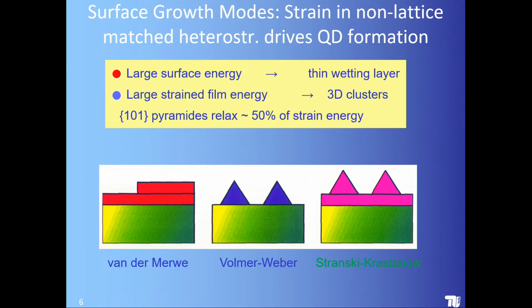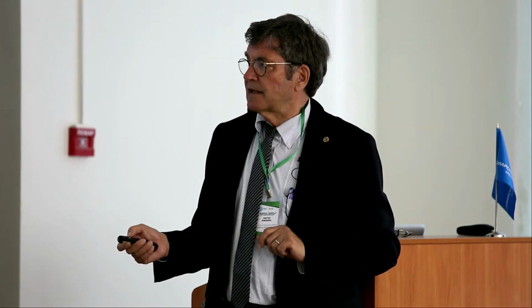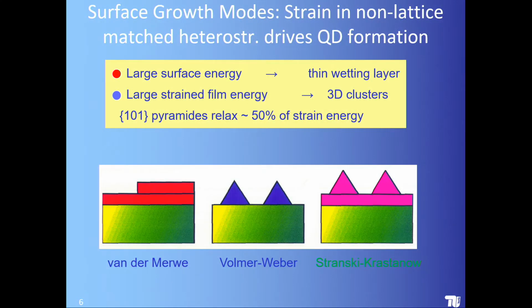So we have two classical growth modes. The Frank-van der Merwe growth mode, which is based on large surface energy. Then you get a thin wetting layer if you deposit a second material on top of a first material. Then you get layer by layer growth. That is the Frank-van der Merwe growth. The second growth mode, if you have large strain film energy, results in three-dimensional clusters. That was discovered by Professor Volmer, professor of physical chemistry actually at Technical University in Berlin before the Second World War, and his co-worker Weber.